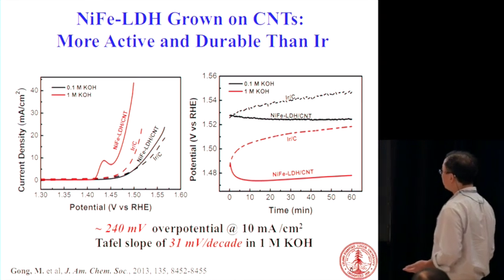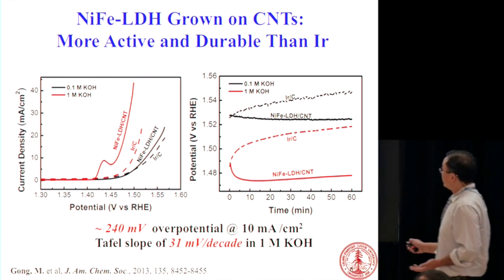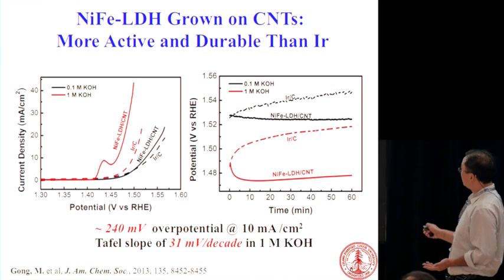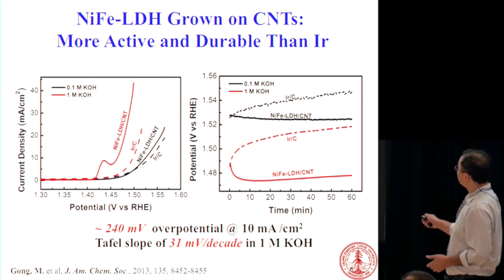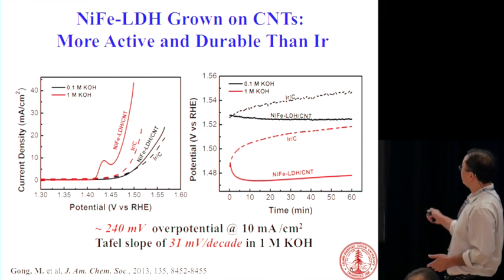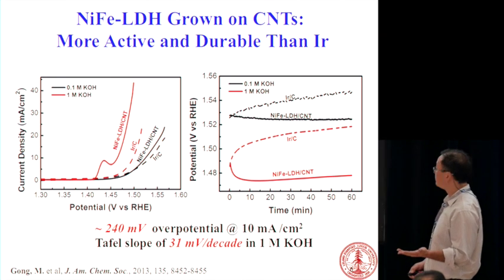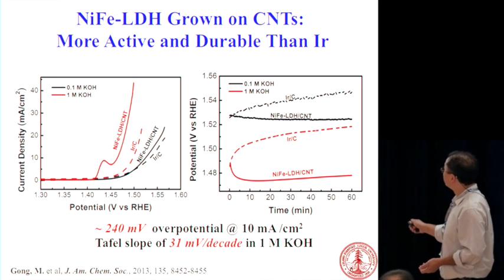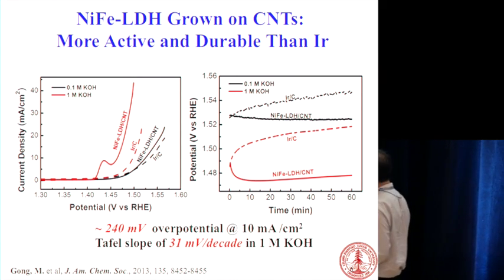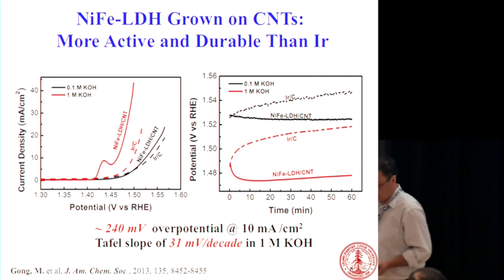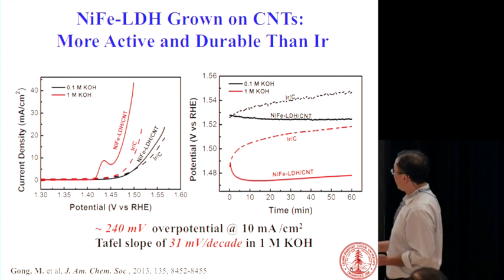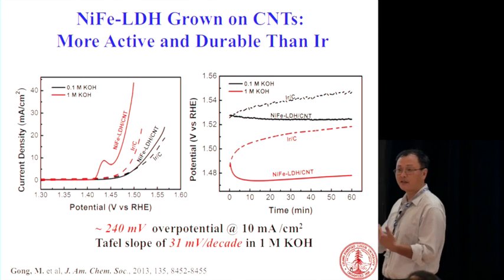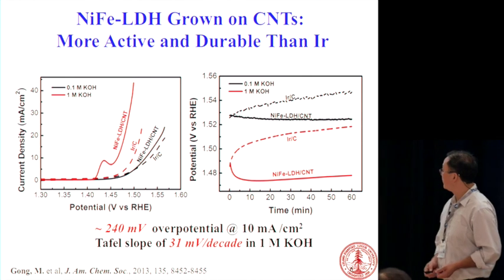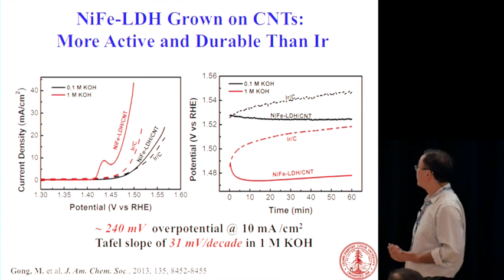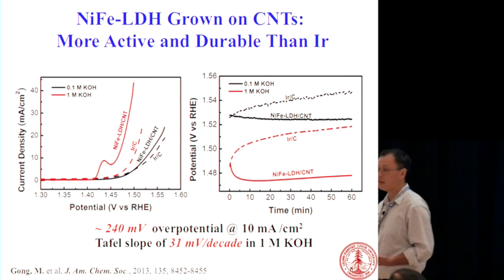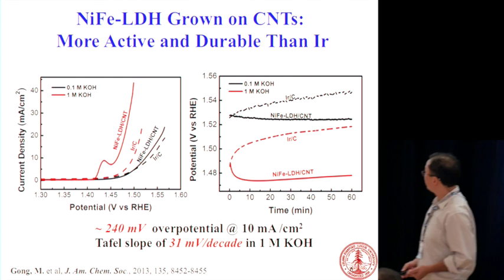This is in KOH solution. And what's more important is it's also quite stable. So this is a constant current curve. You can see with the LDH, the voltage you need to produce oxygen is stable. Okay, it doesn't decay. But for iridium, it actually decays. So there's a stability problem for iridium. So this is really quite active. It's not quite 1.23 volt. Okay, you still have 200 millivolt, 250 millivolt overpotential because it's a 4-electron process. So there's a lot of kinetic barrier.